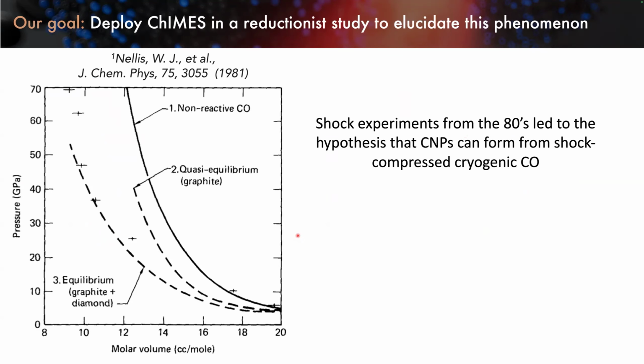If we look at their data, these crosses are experiments, and these lines are predictions from different equation of state models. What we see is that for weak shocks, we end up on this solid curve, the non-reacted equation of state. For stronger shocks, we find ourselves falling on a curve that accounts for the formation of carbon products. If you read through this paper, they suggest this might indicate nanoparticles are being formed - carbon nanoparticles - but they never really performed any recovery to assess that hypothesis.